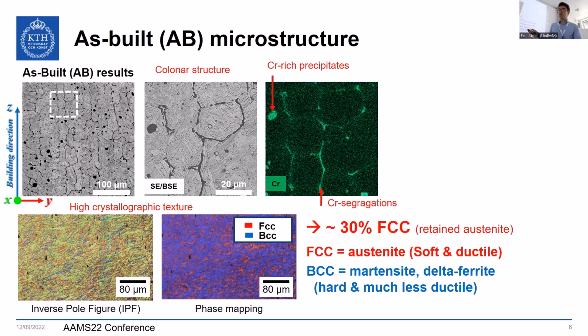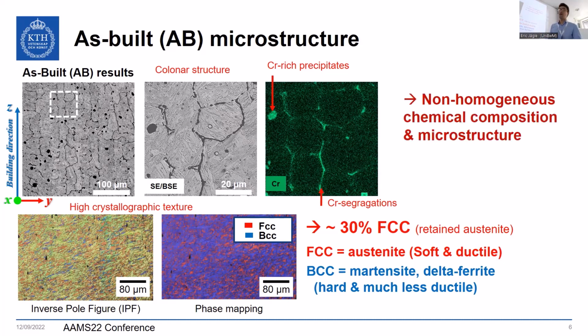Then you also have a dual phase material with FCC austenite and BCC, which can be martensite or delta ferrite. We can say that this FCC is more the soft and ductile phase, whereas this BCC is more hard and less ductile. In the end, you have something like 30% of FCC. What can be put forward is that we have a quite non-homogeneous microstructure in terms of chemical composition and features, which probably leads to these poor mechanical properties that we'll see after.